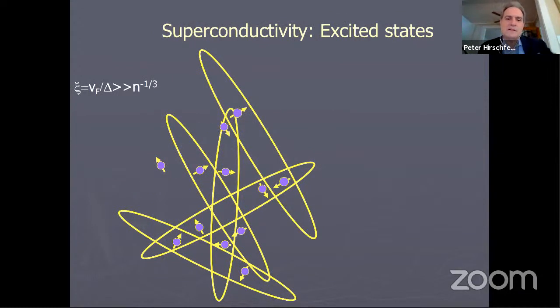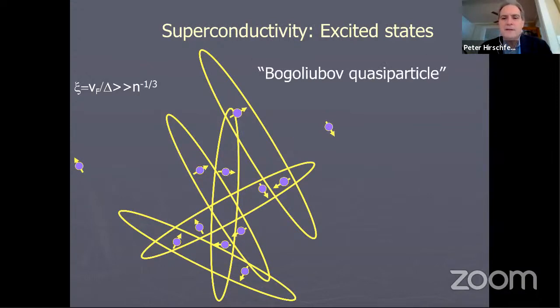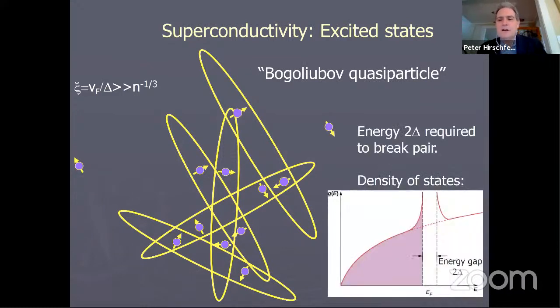Okay, so what's an excited state above the ground state? Well, you can break one of these pairs. And in the process, you generate two fermionic excitations, which are known as quasiparticles, and they can propagate on their own until they repair, and they determine the thermodynamics of the system. Those are called Bogoliubov quasiparticles. The energy required to break a pair is a distinct energy that characterizes the superconducting state, and it's related to the order parameter I showed you before. It's called delta. So if we look at the density of states of this quantum mechanical system, there is a gap that opens up around the Fermi energy of 2 delta.